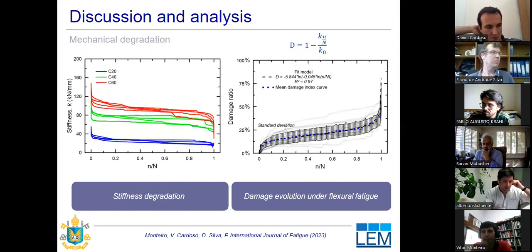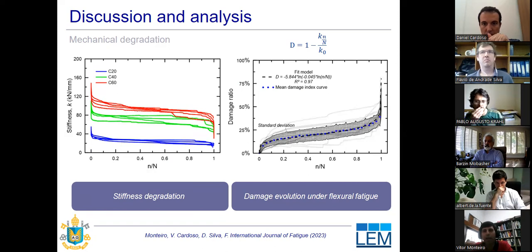So here we have the first graphs of stiffness decaying along the fatigue life. It's possible to verify an almost linear decay of the stiffness after the first cycles until reaching the rupture. It's possible to verify that the stiffness is directly correlated with the residual strength, since the more fibers in the material, the higher the stiffness recorded.